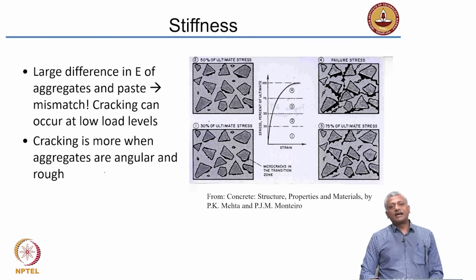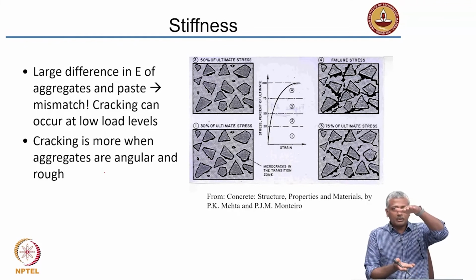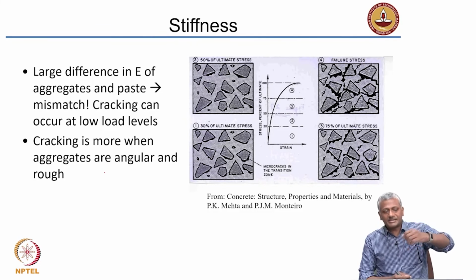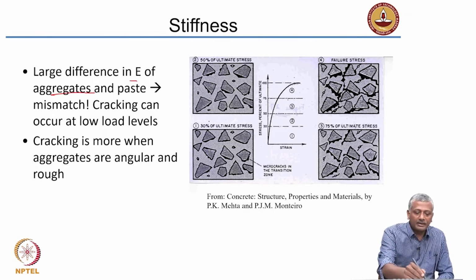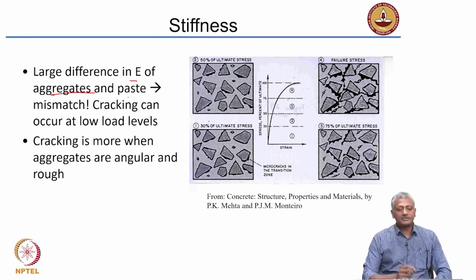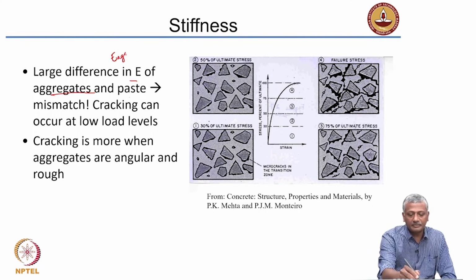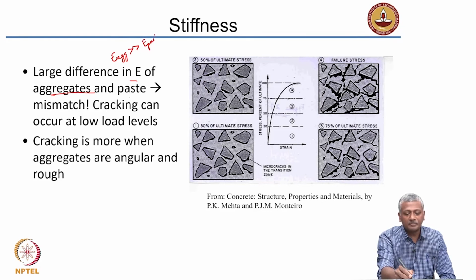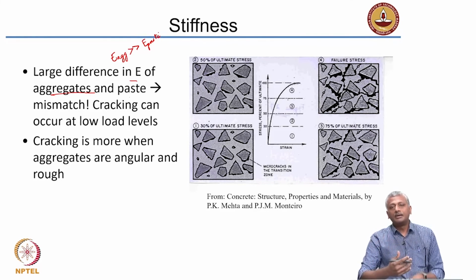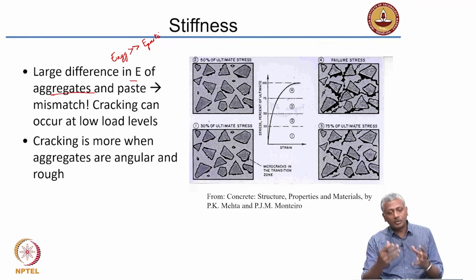What about the stiffness of the aggregate? Why is it important? Now, concrete is a composite material, aggregates are embedded inside paste. When you start loading concrete, I already talked about the fact that stiffness of the aggregate is generally much more than stiffness of the paste. So, modulus of elasticity of aggregate is generally much more than modulus of elasticity of paste. Again, this is for normal concrete. When you start strengthening the paste in high strength concrete, it becomes more and more equal. It never becomes totally equal, but becomes more and more equal.